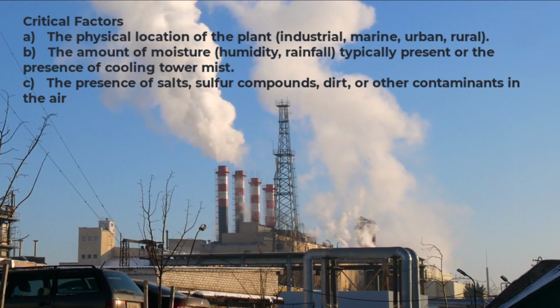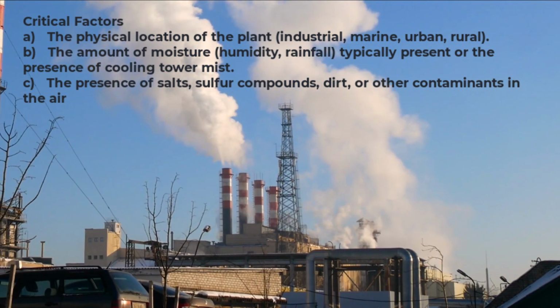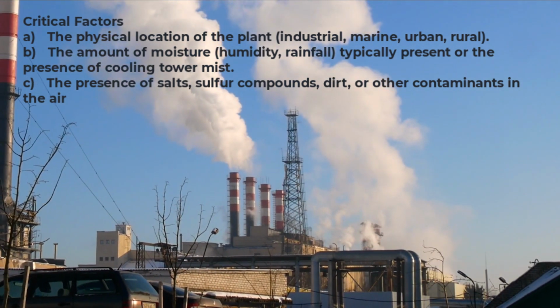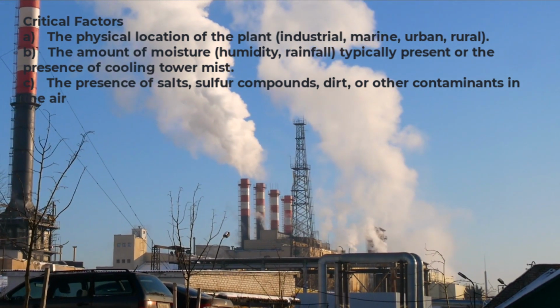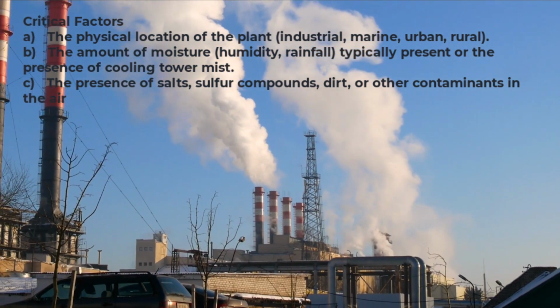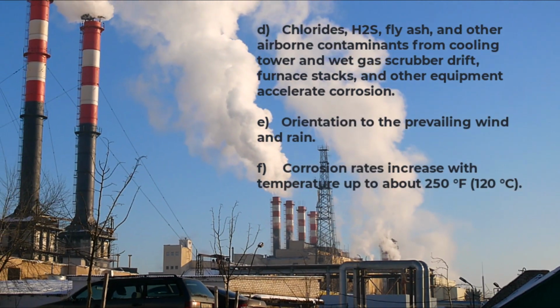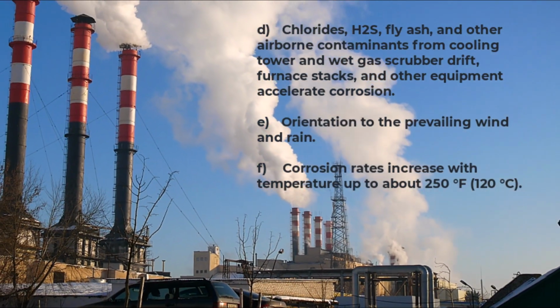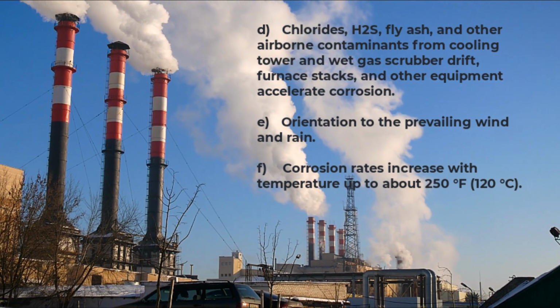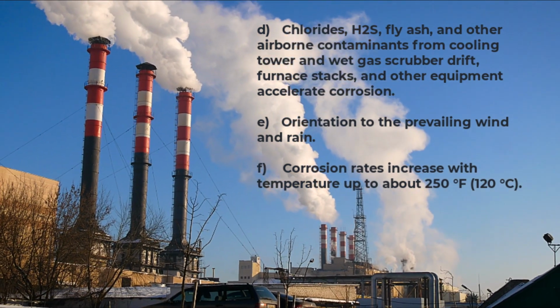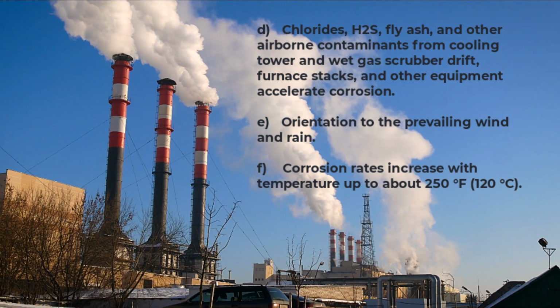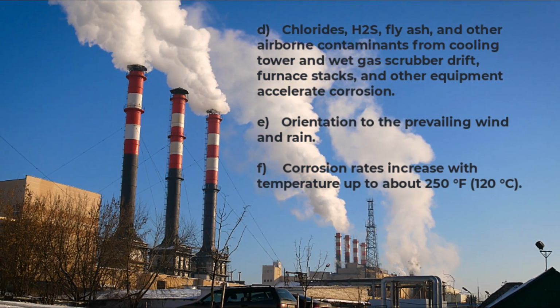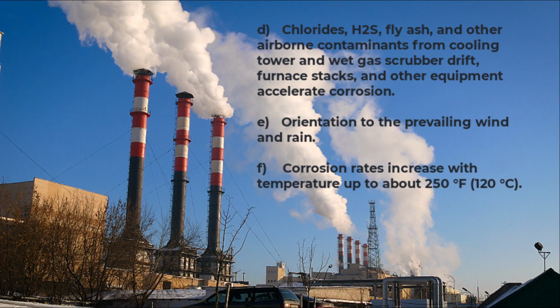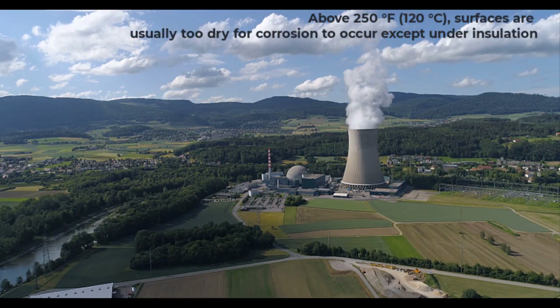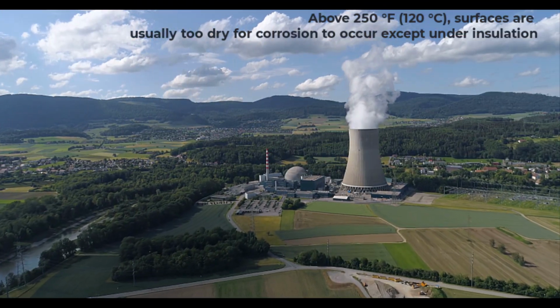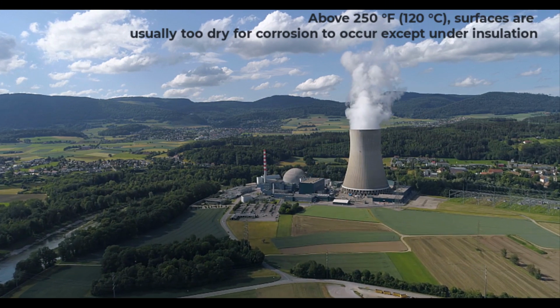Critical factors include the physical location of the plant, the amount of moisture, humidity and rainfall, the presence of salts, sulfur compounds, dirt and other contaminants, chlorides, H2S, fly ash and other airborne contaminants from cooling towers, orientation to the prevailing wind and rain. Corrosion rate increases with temperature up to about 250 F, 120 C. Above 120 C, surfaces are usually too dry for corrosion to occur except under insulation.